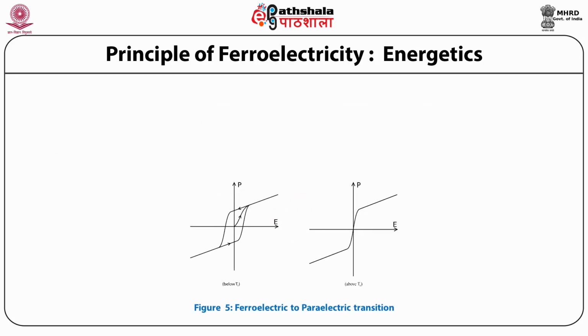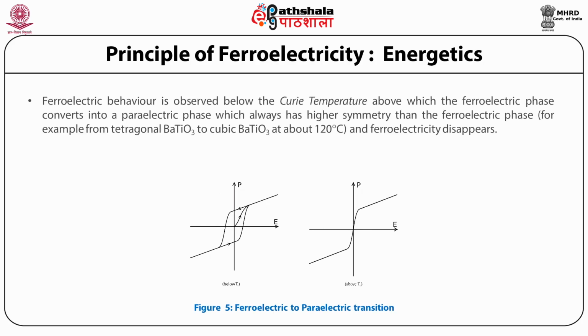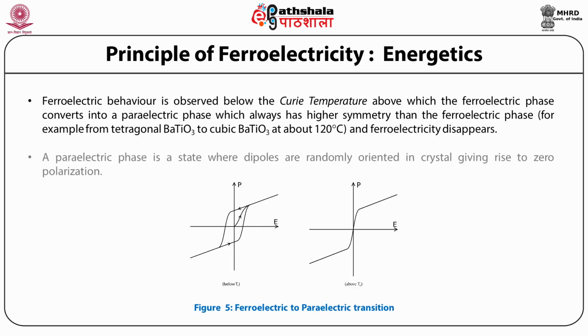So students, you can see the ferroelectric to paraelectric transition, which is shown by this figure. The ferroelectric behavior is observed below the Curie temperature, above which the ferroelectric phase converts into the paraelectric phase, which always has higher symmetry than the ferroelectric phase. For example, from tetragonal barium titanate to cubic barium titanate at about 120 degrees Celsius, and the ferroelectricity disappears. A paraelectric phase is a state where dipoles are randomly oriented in crystals, giving rise to zero polarization.